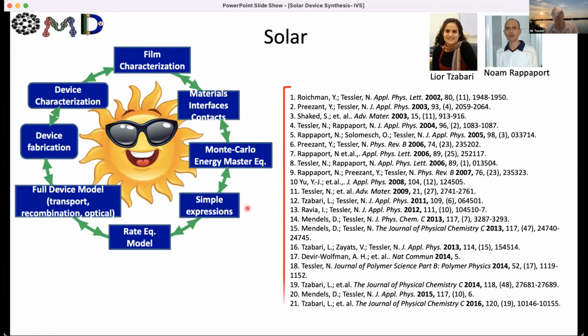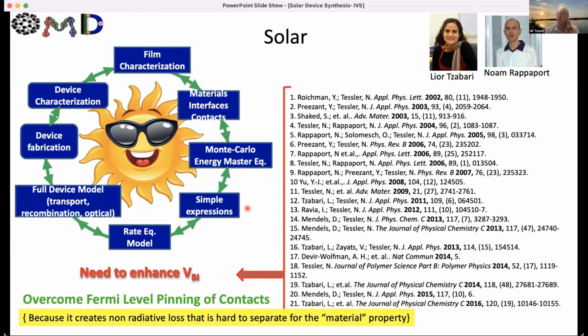And from this long journey, we managed to find out that the open circuit voltage of solar cells is really limited by the built-in potential. And this is something that turned out to be very surprising, because the one thing people always like to say that is excellent about organic materials is that there is no such thing as Fermi level pinning, but there is, in any organic material or in any semiconductor. And it is also very hard to decipher that this is what is killing your device open circuit, because it just introduces another loss mechanism. So many people ignore it, and some still try to deny that it exists.